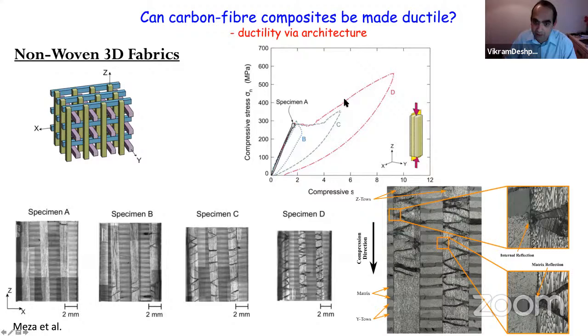So all that's happening along this curve here is that you're getting more and more kinking. And so while, of course, we have not changed the ductility of the carbon fiber itself, the overall specimen ductility has gone up because you're consuming the tows with these kink bands rather than just getting one kink band that is going unstably across the structure, basically. So that's what's happened in this case here.